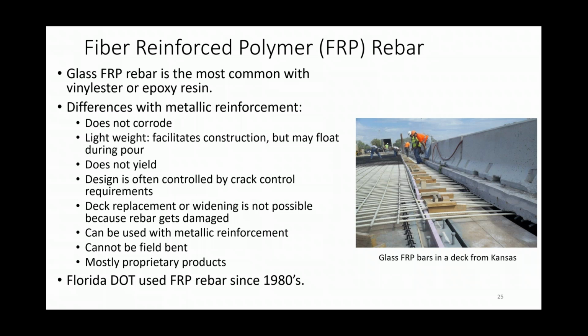Okay, so I'll start with fiber reinforced polymer or fiber reinforced plastic FRP rebar. There are different kinds of FRP rebar: glass FRP, carbon, aramid, but glass tends to be the most common and cheaper. So most of our discussion focused on glass FRP rebar. And for this one, we heard from Florida DOT, which has used FRP rebar since the 80s. They have a great website just dedicated to their FRP research. They have essentially developed concrete applications with FRP rebar. Although most of their applications are for substructure units, because in Florida, the corrosion starts from the salt water, not from the de-icing salt. So you see a lot of piles and substructure units, essentially.